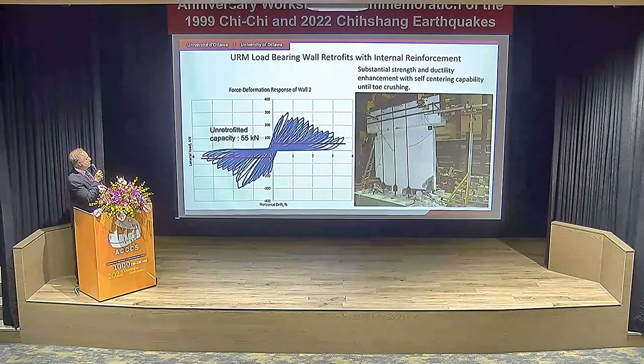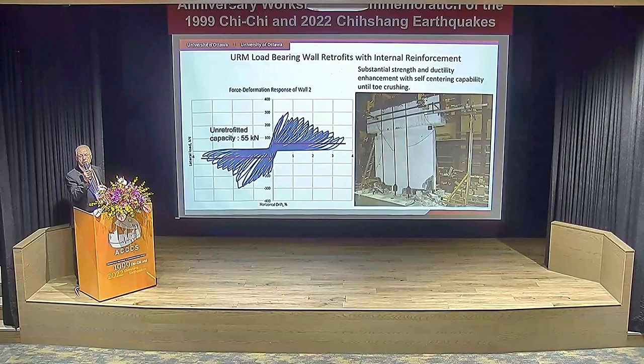And you can see there was a significant improvement in strength from 55 to 300, but there were many more cycles without strength decay. But this time we did fill all the gaps with concrete, and hence there wasn't any web crushing failure. Eventually it failed through toe crushing, concrete crushing.